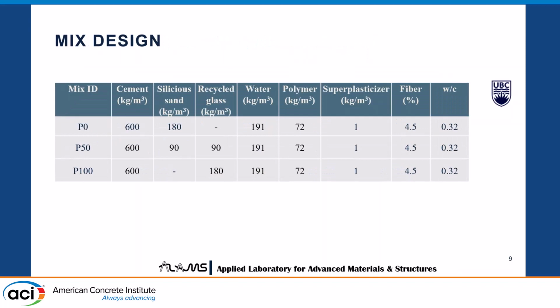And this is the mix design that we use. So we have three mixes I mentioned, P0, P50 and P100. P0 is the control one with 100% sand. Then P50 has 50-50 and P100 has 100% recycled glass. So if you look at the polymer, it's actually 72 kg per meter cube, which is 12% of the cement content, and we had 4.5% of glass fibers by volume.